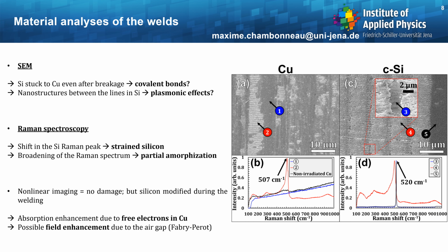One may note that even if during the nonlinear propagation imaging there is no damage formed, here silicon is modified during the welding. And this may originate from an enhancement of the absorption due to the free electrons in copper, and also a possible field enhancement due to the air gap, so a Fabry-Perot cavity.